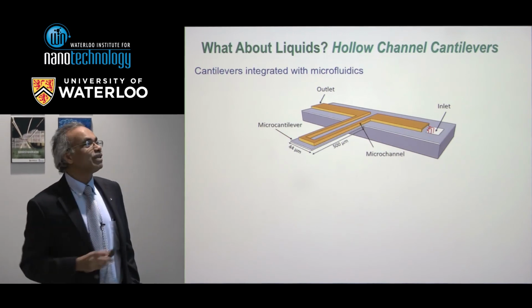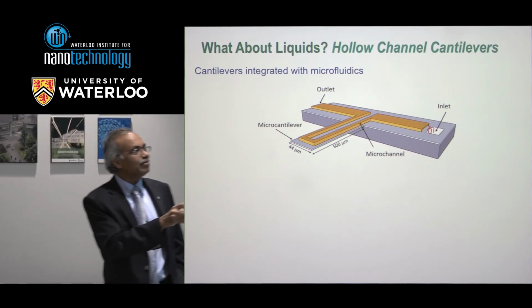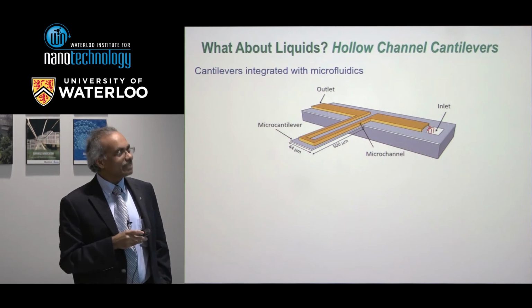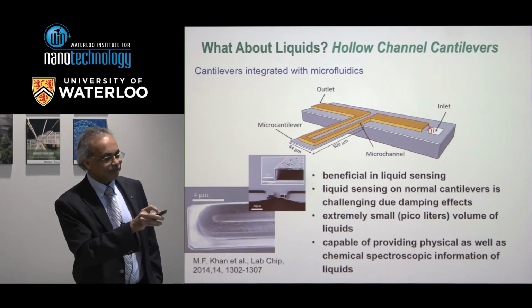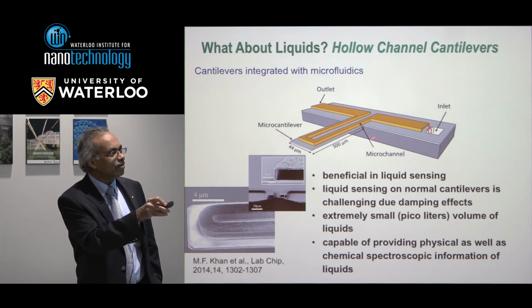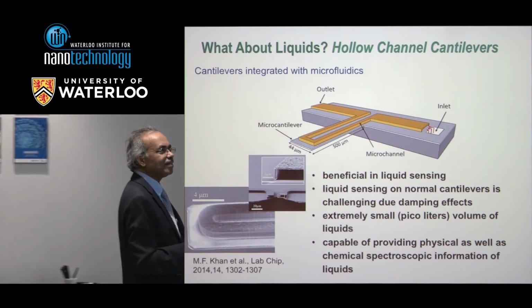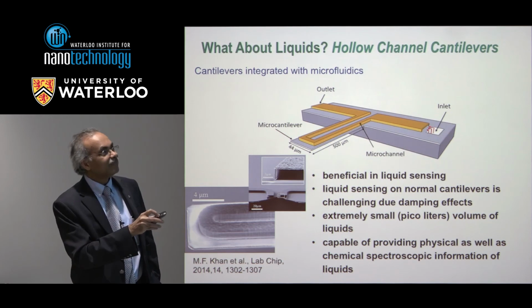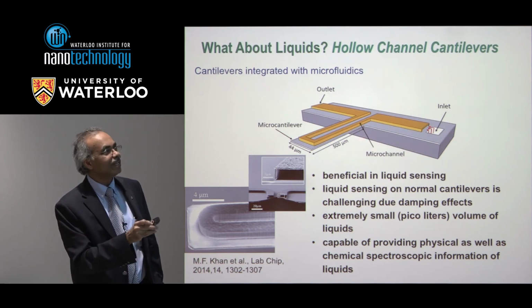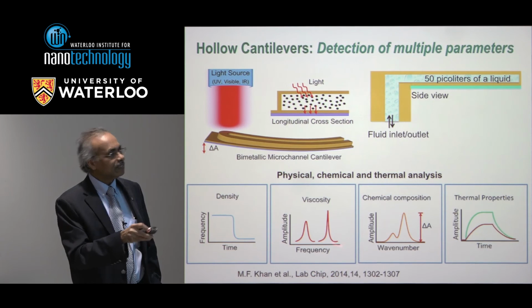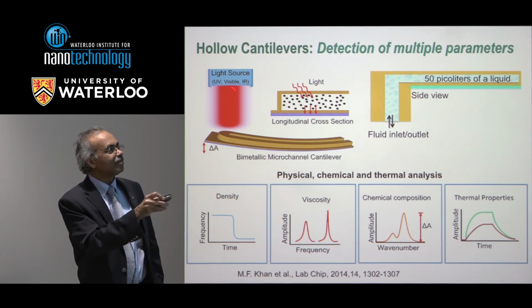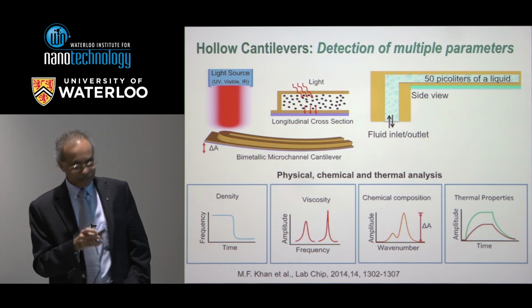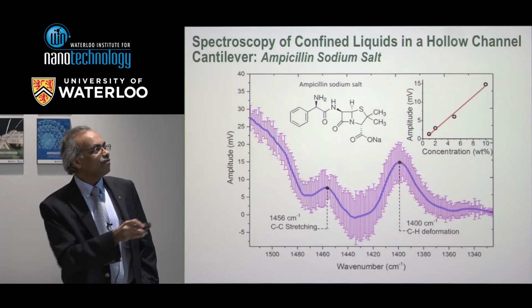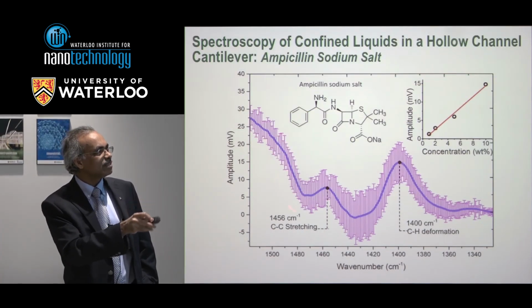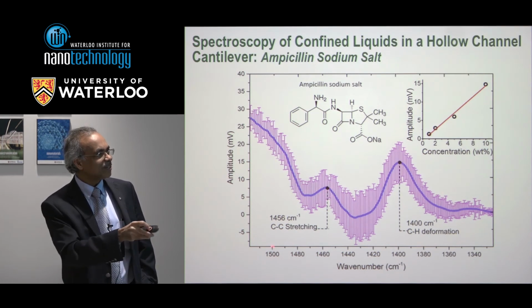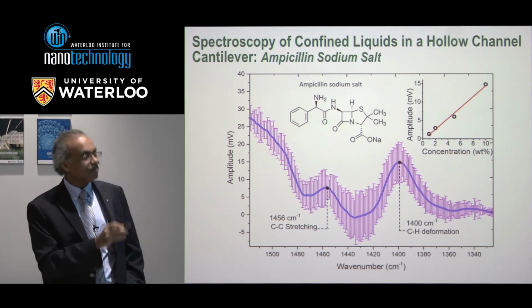So people said, okay, vapor is fine, what about liquid? So we made a cantilever and then formed a little microfluidic channel on the top of it. And so this is the channel, so you can fill it with the liquid. Scott Manalis at MIT started this thing, so we borrowed it from him. And now we can get spectrums of liquid in it. You can look at the density, viscosity, chemical composition by spectroscopy, and thermal properties. This is ampicillin salt, 50 picoliters inside the cantilever, and this is the spectrum. This is a mechanical bending of the cantilever.